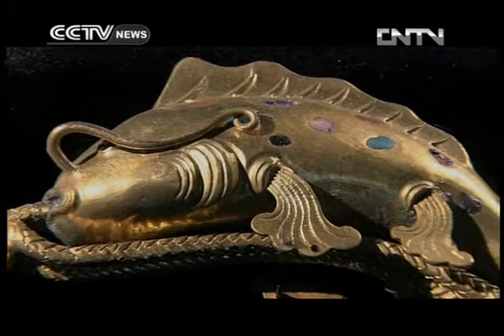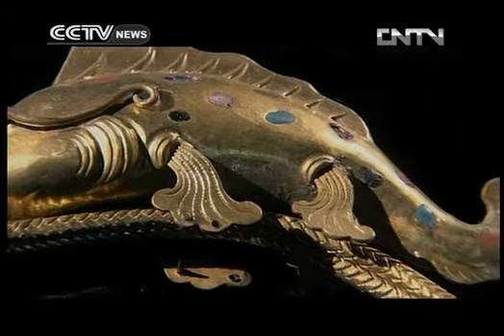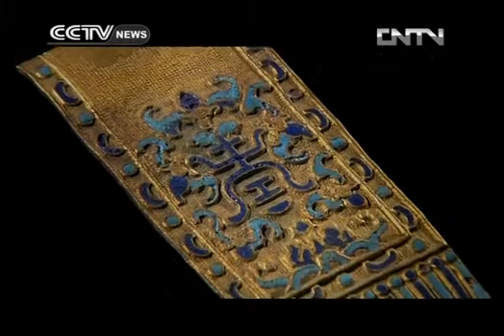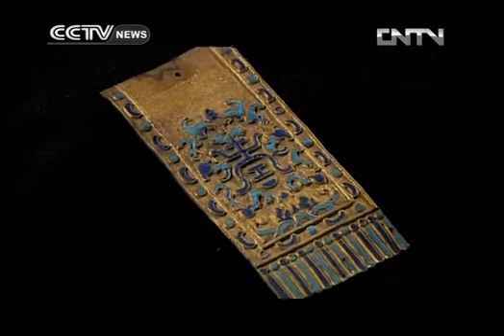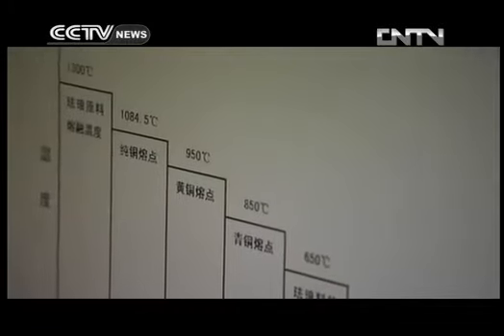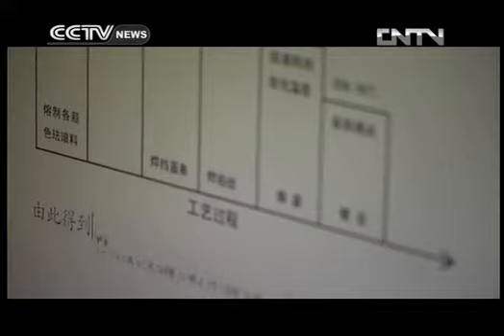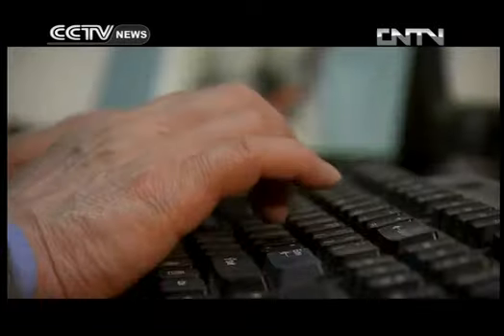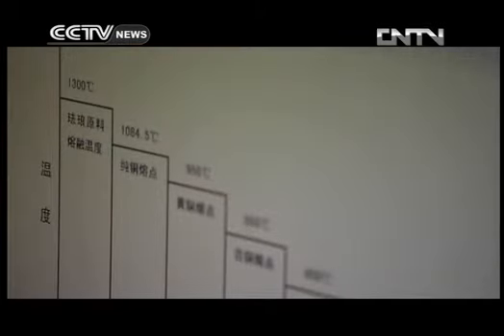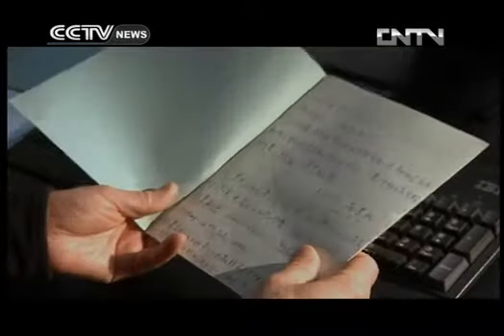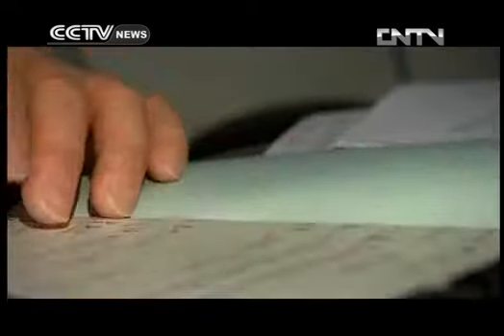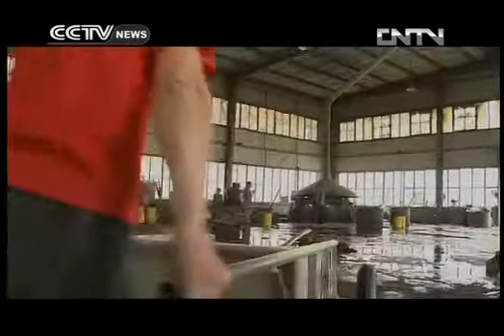The delightful luster of a cloisonne object is obtained through firing for 7 to 8 hours. The temperature must be above 1200 degrees. However, since the melting point of the red copper base is only 1084 degrees, the task is seemingly impossible. The craftsmen of the past developed a complex method to solve this problem. The same method is still used by their counterparts today.